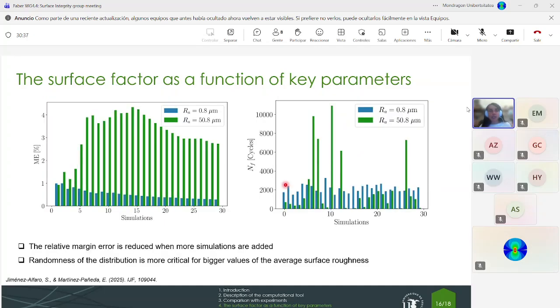Here you can see how the relative margin of error and also the number of cycles to failure change when we consider the sample size, so the number of simulations. You can see that the margin of error is reduced when we increase the number of simulations. And also you can see in this graphic how the average surface roughness plays an important role in the stochasticity of the phenomenon. When we have low values of the average surface roughness, more or less the number of cycles is homogeneous. But when we have a big value, the peaks are really different. So we can get really different results from one simulation to another. And this is why we need to consider a sample size and this relative margin of error. So the randomness is directly related to the value of the average surface roughness.